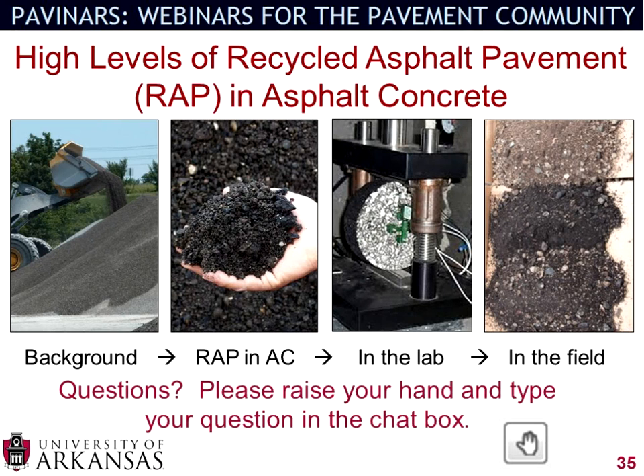The next question from Andrew is, can RAP be used in treatments other than hot mix and warm mix, such as slurry seals, microsurfacing, and other surface treatments? Are any states doing this? For slurry seals and microsurfacing, those usually tend to use a much finer mix. And I think that the benefits of RAP for using in asphalt applications comes from using the larger aggregate sizes. So you have a nice hard aggregate particle that has a lot of asphalt coating it.